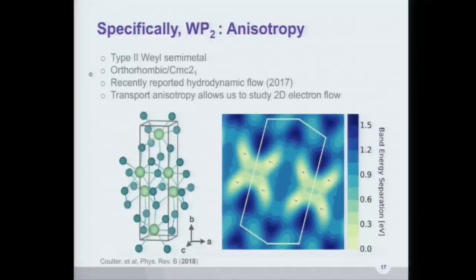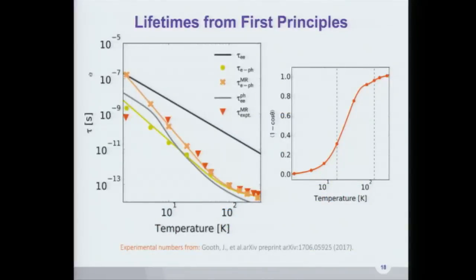OK, so we got into it with thinking of tungsten phosphide as our kind of model case. This is a type 2 Weyl semimetal. It's very low symmetry. It's CMC 2.1 if you think in those terms. And it has this very strong anisotropy, so there's a particular plane that is preferred for this 2D-like transport, and everything else is not. That just kind of is ignored. So if you look at these crystals, if you look at a picture of the whole thing, it kind of has this needle-like shape, right? So you can tell that there must be one direction in which flow is preferred and the other where it's probably a bad idea.